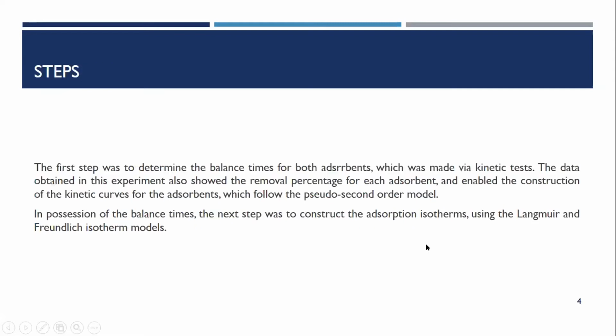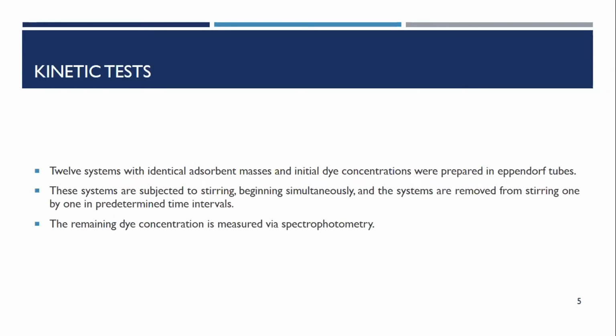The first step was to determine the balance times for both adsorbents, which was made via kinetic tests. The data obtained in this experiment also showed the removal percentage for each adsorbent and enabled the construction of the kinetic curves for the adsorbents, which followed the pseudo-second-order model. In possession of the balance times, the next step was to construct the adsorption isotherms using the Langmuir and Freundlich isotherm models.